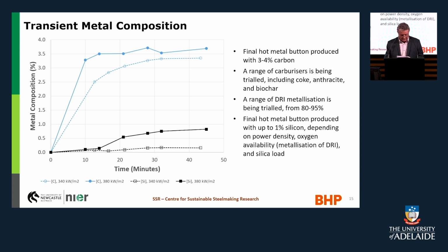This graph here is showing you transient metal composition. The top curve there is for carbon content in metal. We're able to get the carbon up above 3%. And the bottom curve is showing you, I think, silicon content. And we've got some results at different power density, okay? So power density is part of the deal of controlling the temperature gradients within the reactor. That's real process stuff, and it's good to be able to do those tests.